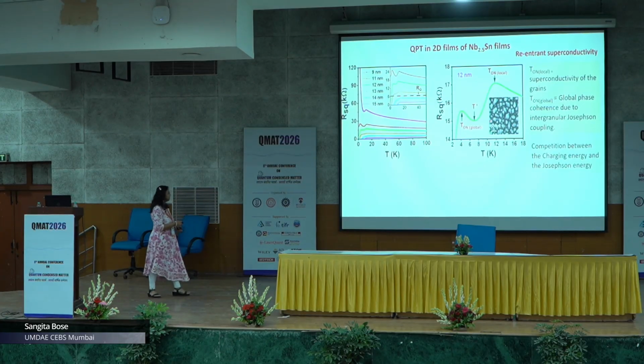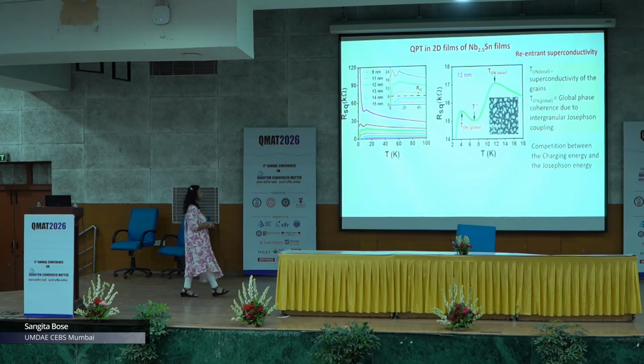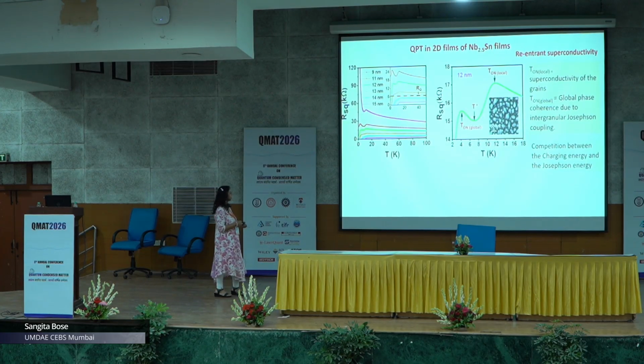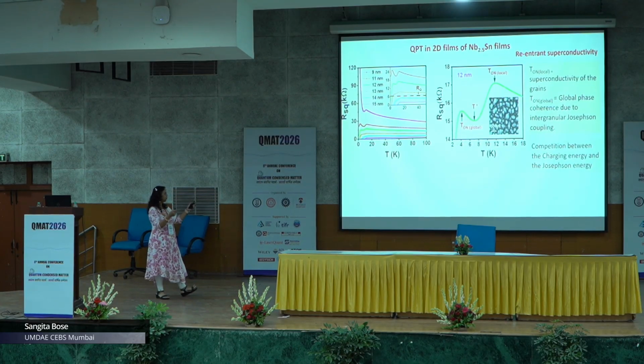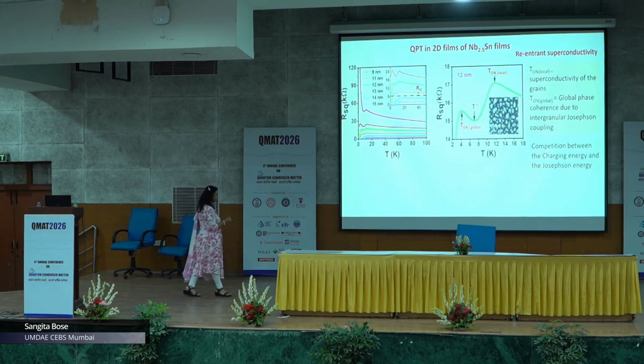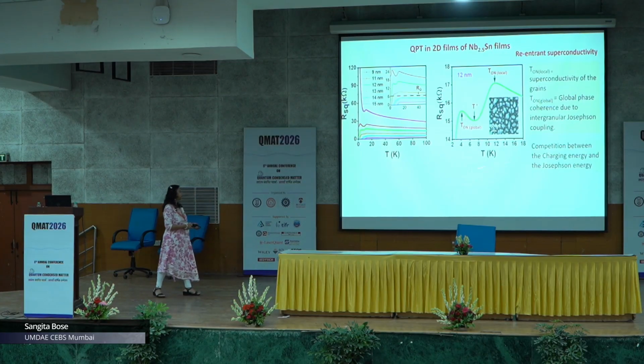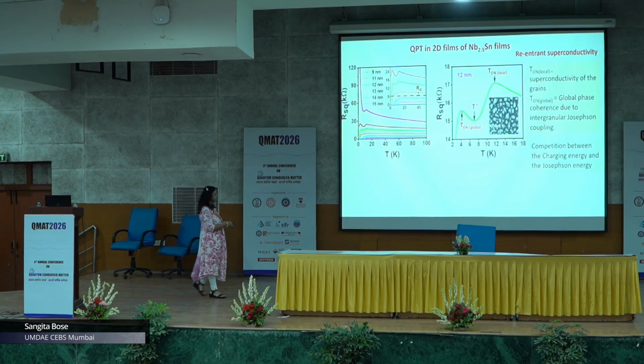Then it starts decreasing. But here the grains are still small, and if the grains are small, you will have a charging energy. It will start dominating, and you will start seeing the resistance increase. However, at this temperature, which I label as T onset global, the Josephson coupling energy, which is coupling my grains, wins over, the energy scale wins over, and you then start seeing this drop. So basically this competition between the charging energy and the Josephson energy is able to explain this double reentrant behavior of superconductivity observed only in these kinds of films.